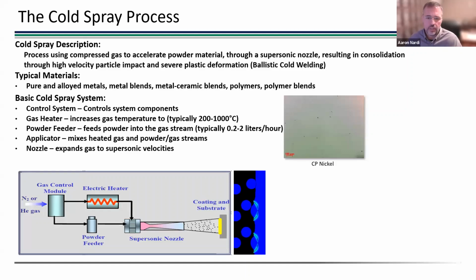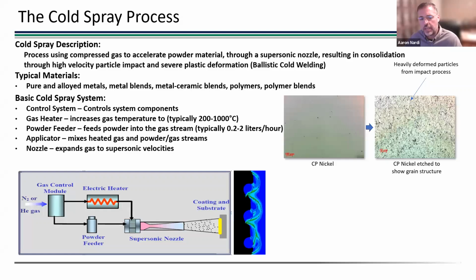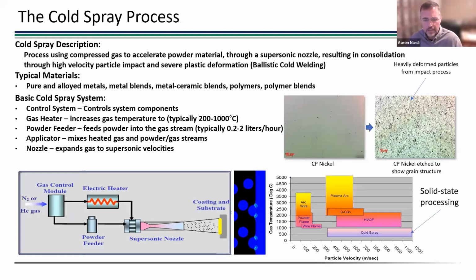This is an example of a nickel. And then when you etch that, you can kind of see that grain and powder structure in the material. It's very heavily deformed, high levels of cold work in the material. And that's really how this process is differentiated from all the other thermal spray processes. It's that solid state nature of the process.